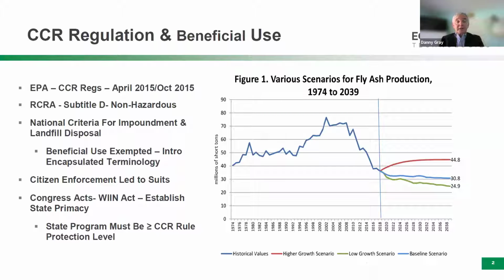Under the RCRA Subtitle D CCR regulations, beneficial use was exempted because that portion of the recycling industry had been very successful for many, many years, and basically needed to be encouraged. Within the CCR regulations, we introduced new terminology that introduced the encapsulated premise, and there was a definitional difference between encapsulated and non-encapsulated beneficial uses. Non-encapsulated beneficial uses were still allowed under a very strict set of criteria. Basically, I refer to them as the no harm criteria, but beneficial use in encapsulated applications was deemed to be preferred and acceptable. And that included things like use as a replacement for cement and concrete.